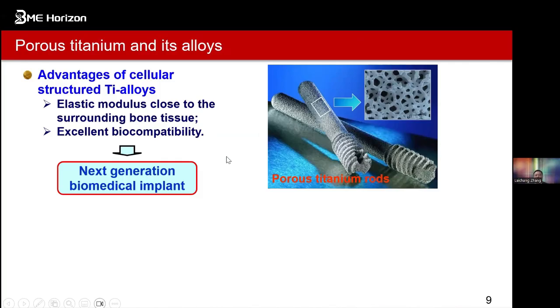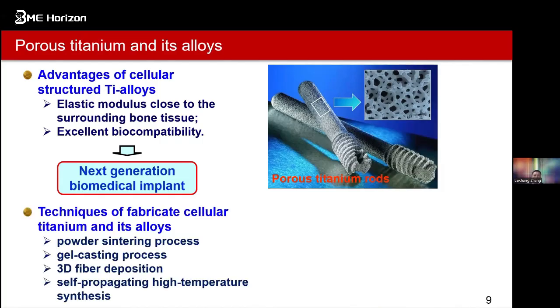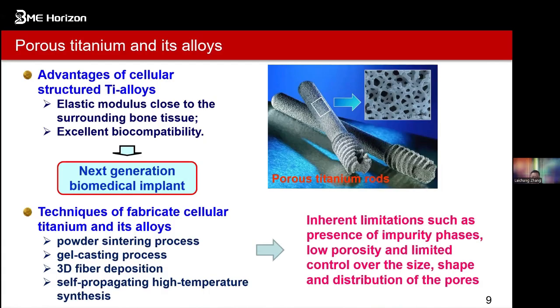And of course, titanium alloys have excellent biomedical compatibility, and can be representative of next generation biomedical implants. In the traditional way, we can produce this kind of porous structure by powder sintering processing, gel casting processing, 3D fiber deposition, and self-propagating high temperature synthesis. But traditional fabrication has inherent limitations such as the presence of impurity phases, low porosity, and limited control over the size, shape, and distribution of the pores.